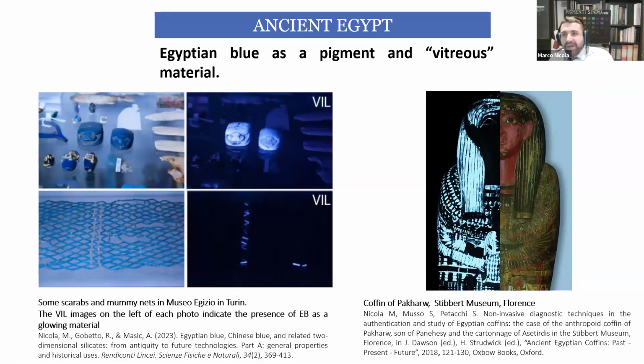They are somehow linked together because the raw materials you use to make them are the same. But the specific material is different because the faience has a core that is sintered silica. So when you break the faience, the inner part is not blue, it's white, because it's sintered silica covered by a coating that is a glass. The coating of the sintered faience is similar to the glass matrix of Egyptian blue.